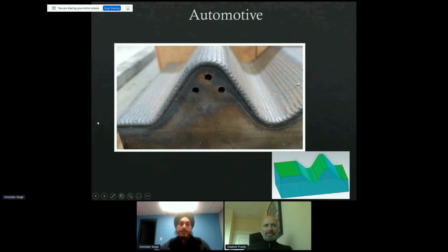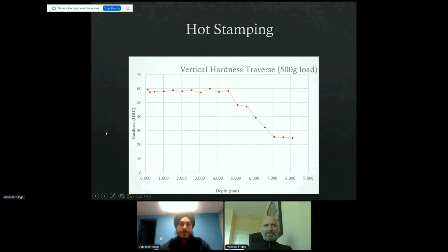Automotive. Recently we made a hot stamping die. We did a cladding with a hard material on the hot stamping die. And just to show you the numbers, the clad was 60 HRC, and this is the base material, which is 30 HRC. So we went from 30 HRC to 60 HRC, and pretty consistently.